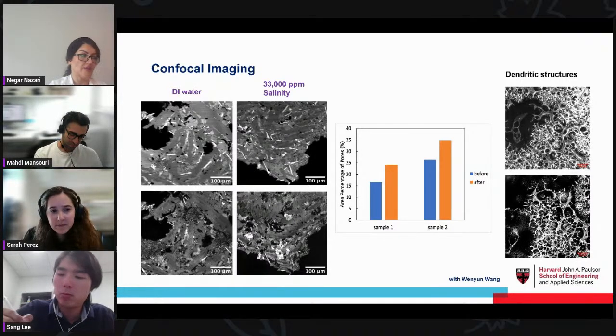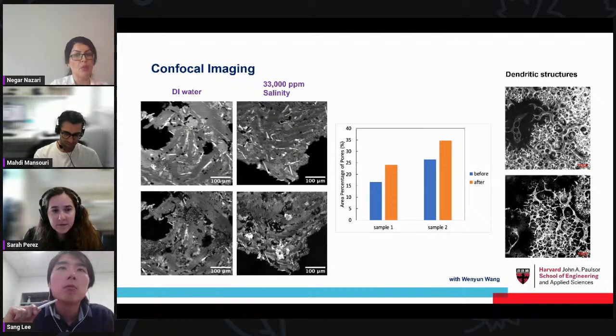The reaction time was very short. The rocks are tight, so we cannot confirm if that change in the pore volume actually happened across the entire volume of the sample. But what we saw is that at least on the surface, we saw a lot of increase in the area percentage of the pores in both of the samples.